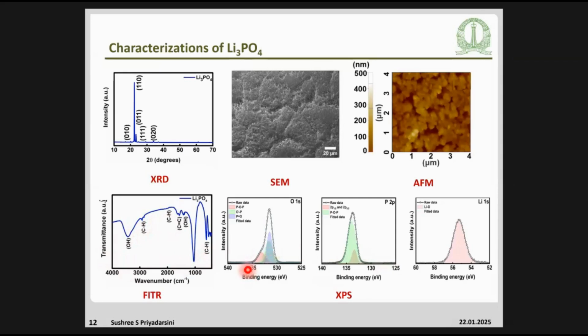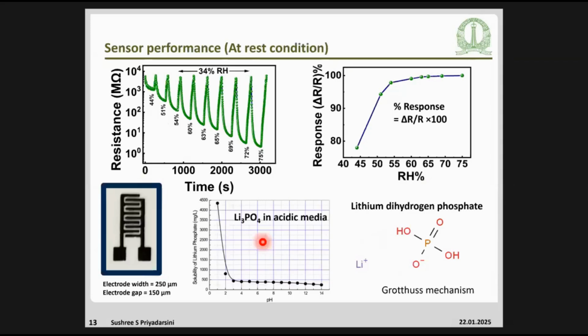To confirm the bonding, we did XPS, and then we found the bonds present in the structure. These are P-O-P, O-P, and then the coordination, how it is. Now let's move to the sensor performance. Now this is the sensor. What it looks like is just the electrode, but we have printed the lithium phosphate on top of that with inkjet printing, because the material was not compatible with screen printing, we decided to go for inkjet printing.